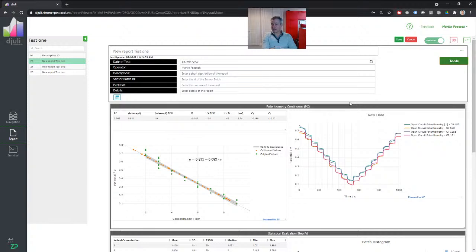So it's not that clever. If we want to know the roughness of the gold, we do use profilometry, where we literally drag a stylus across the surface and it bounces up and down, and that tells us our roughness. If you ever Google Zimmer Peacock profilometry, you'll see that we do profilometry to measure the roughness. To measure the thickness, we literally saw it in half and have a look under a microscope. So it's not exactly rocket science what we're doing.